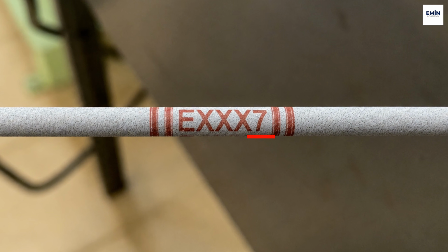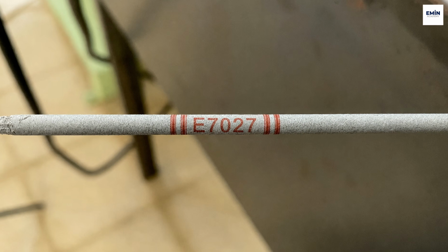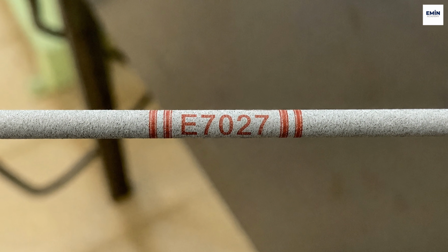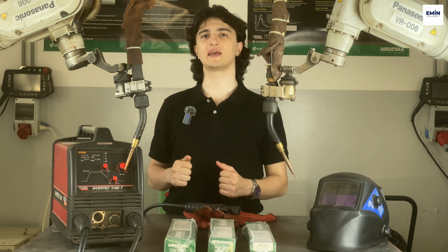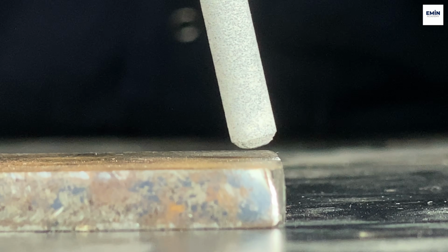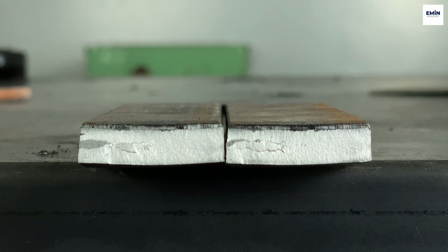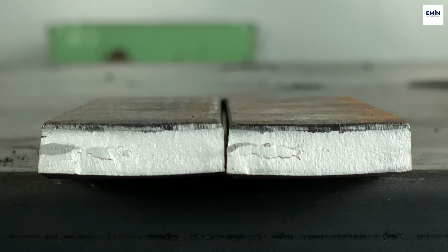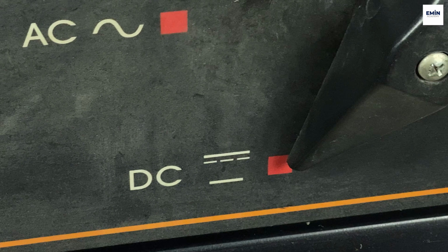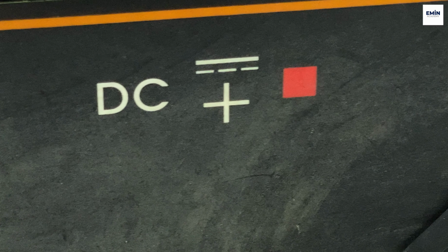7. Iron oxide and iron powder coated electrode. E6027 or E7027 electrodes are examples. The deposition rate is high and it leaves more weld metal. It's generally used for filling welds of thick parts in flat and horizontal positions. It can be used with AC, DC electrode negative and DC electrode positive.